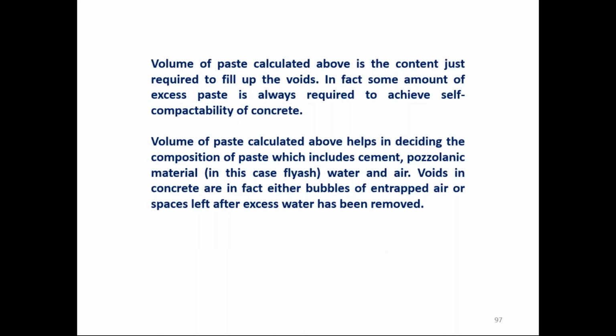So like this, packing density has to be determined by the practical bulk density method, and we can find out the volume of paste required. Volume of paste calculated above is the content just required to fill up the voids. In fact, some amount of excess paste is always required to achieve self-compactability of concrete. We cannot define self-compactability otherwise; the same paste may be sufficient to get, let us say, 40 mm slump or 60 mm slump, or even for pumping concrete about 100 mm slump by adding a suitable admixture of the required dosages. So you have to increase the paste volume by some amount.